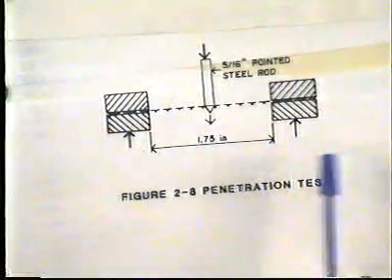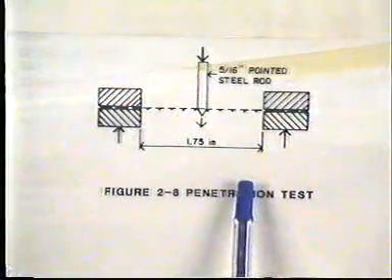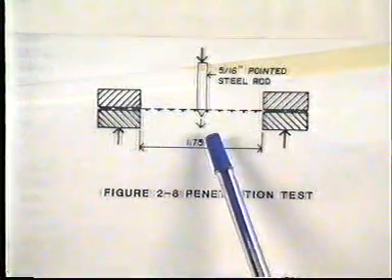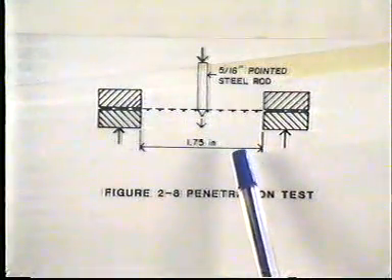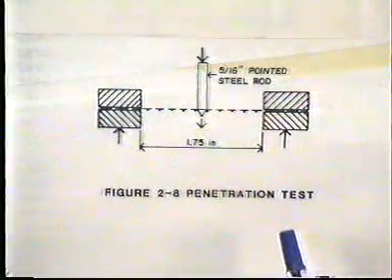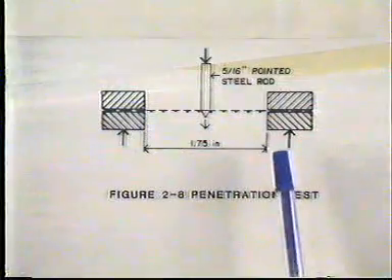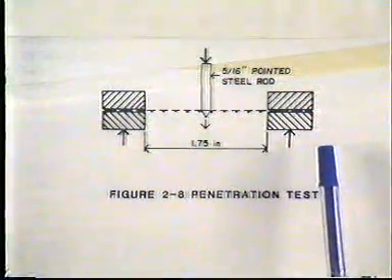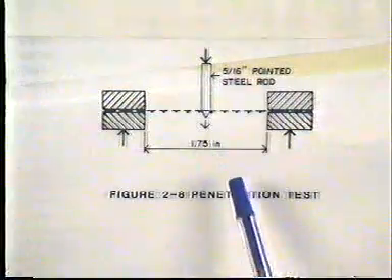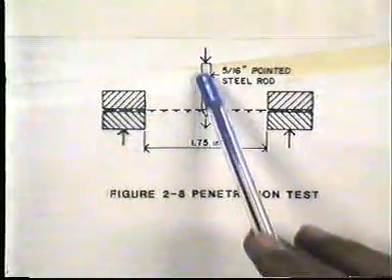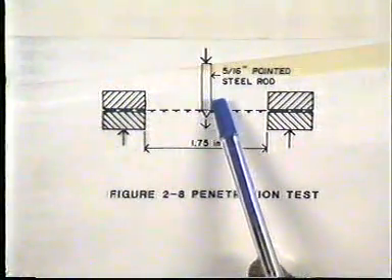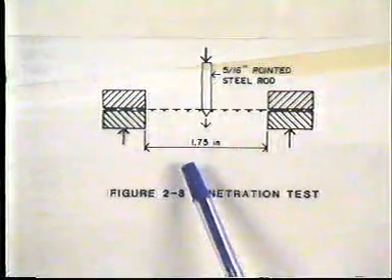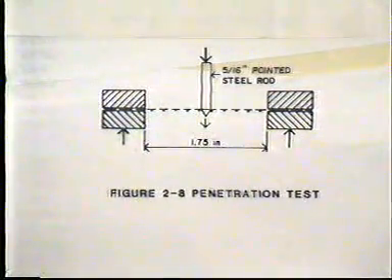However, there is difficulty in establishing the exact diameter, since most geotextiles have an elastic range. A variation of this test method can be conducted by dropping a pyramid, which better simulates very angular fill material.